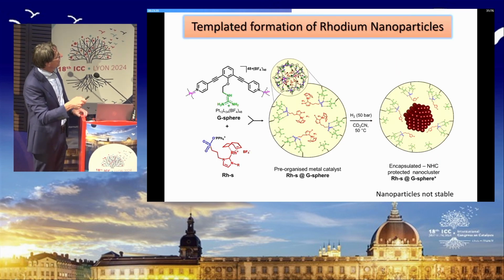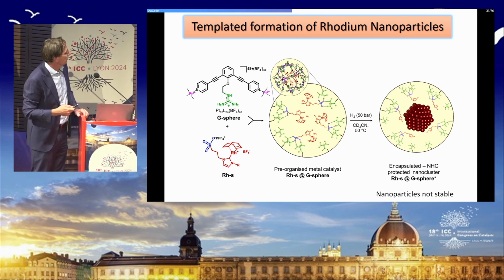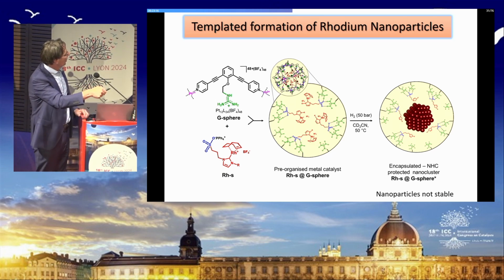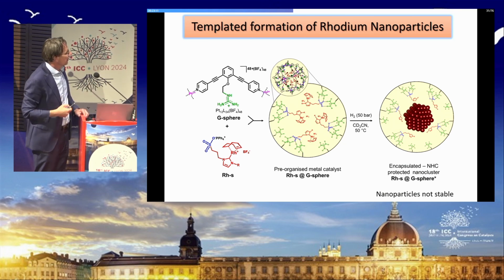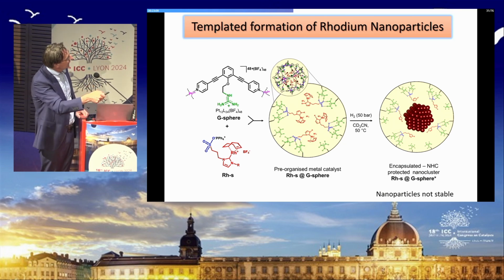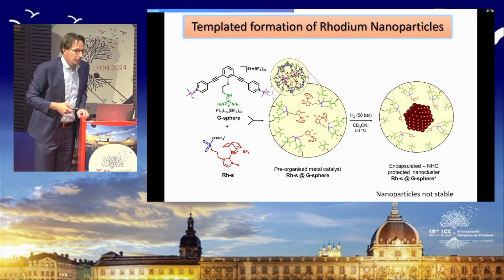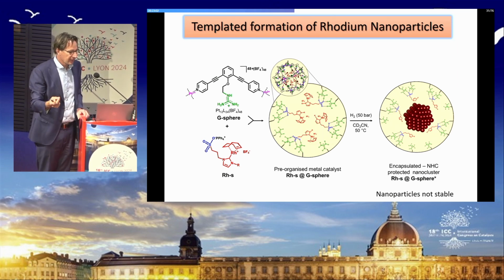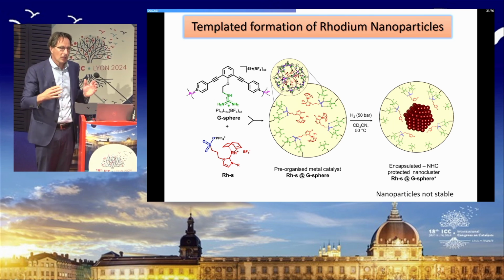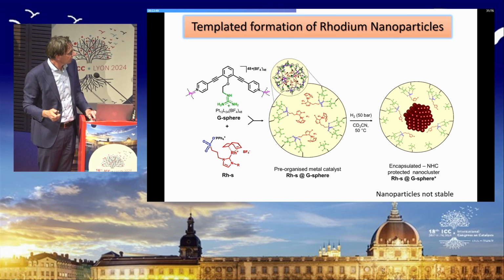So next we were interested to see if we can extend it to rhodium nanoparticles. So we made a rhodium carbene analog that was also bound into these cages. And then we did reduction under reductive conditions. We formed the nanoparticle, but we found that the nanoparticle is not as stable. So the iridium nanoparticles we can keep for months in solution and they remain the same. And these type of rhodium nanoparticles, they become larger after overnight.